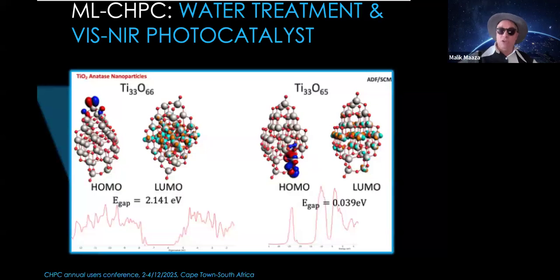Not only UV, but solar radiations, and it's there where it's free. The sun has more than 35% of its radiation in the visible range. Therefore, this titanium with the oxygen defects on the surface will be active to solar radiations and not to the UV specifically.